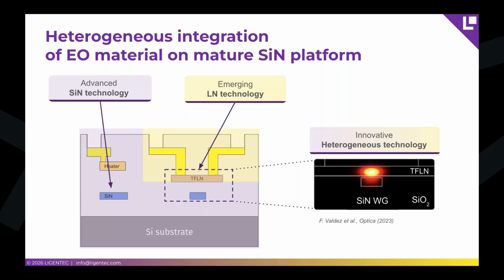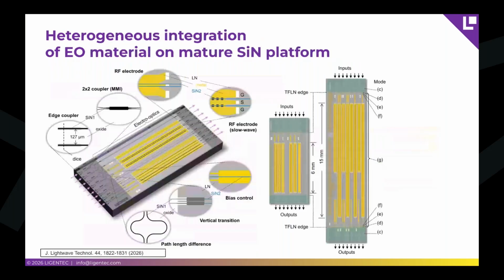We use our advanced nitride technology that is established since many years and running in a 200 millimeter CMOS line, together with lithium niobate technology to create a hybrid mode between the nitride and the lithium niobate. That is definitely happening in a different line. So lithium niobate is not allowed in a CMOS line. So the integration of lithium niobate is happening in a different line.